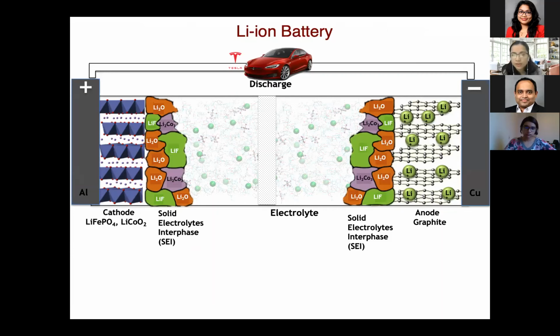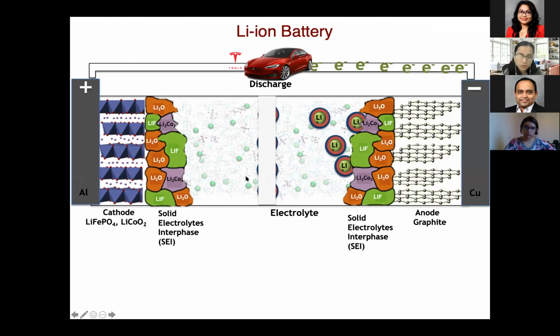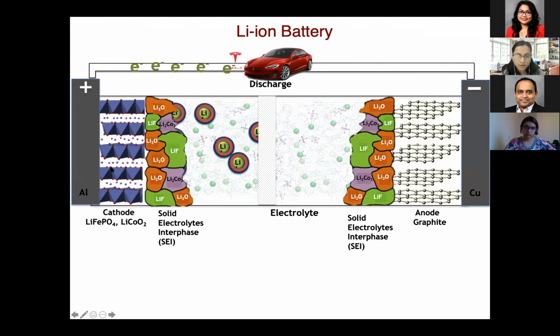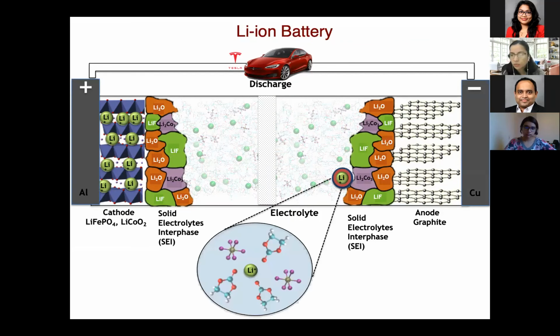When you discharge a battery, the lithium ions start migrating from the anode side, travel through the electrolyte, and intercalate into the cathode. The exact reverse process takes place when we are charging the battery. I would like you to remember 2 things here. One is, when the ions are in the solution, they are surrounded by the anions and solvent molecules, which form this solvation sphere around the cation. I'll be talking a lot about these solvation spheres and how they affect the performance of the battery.